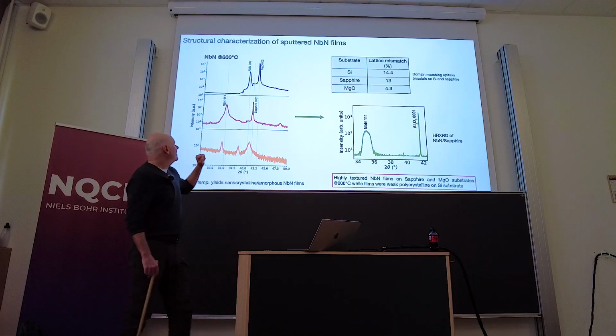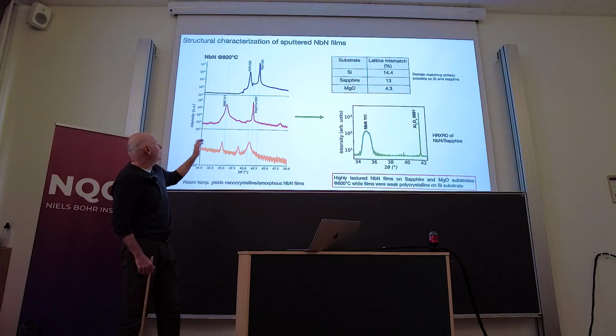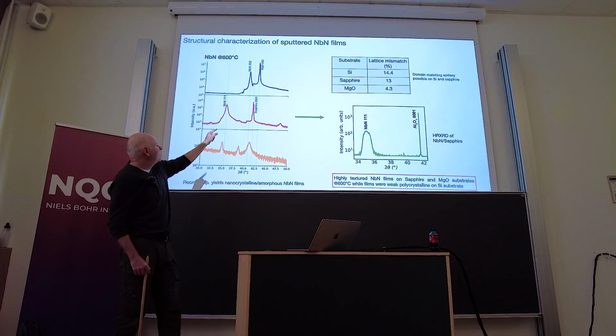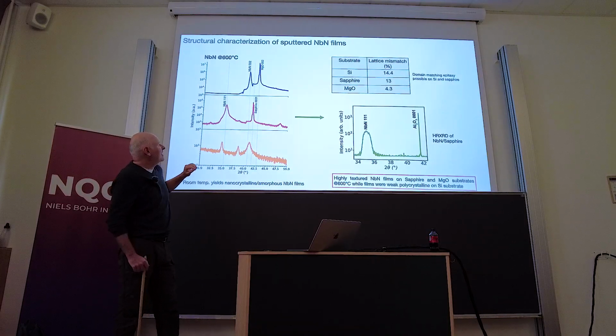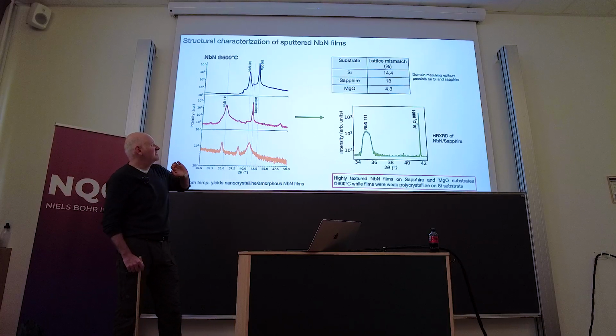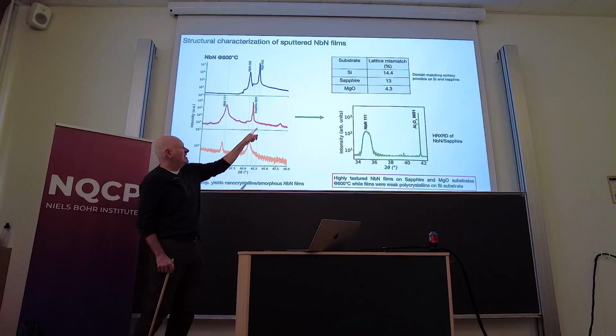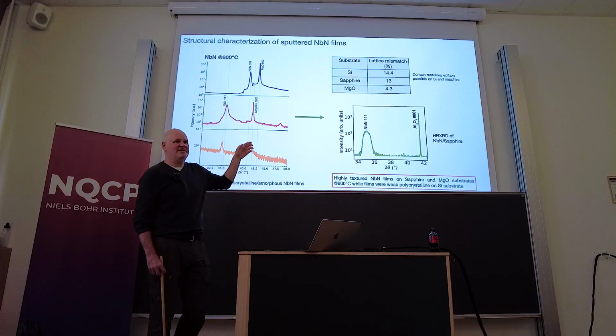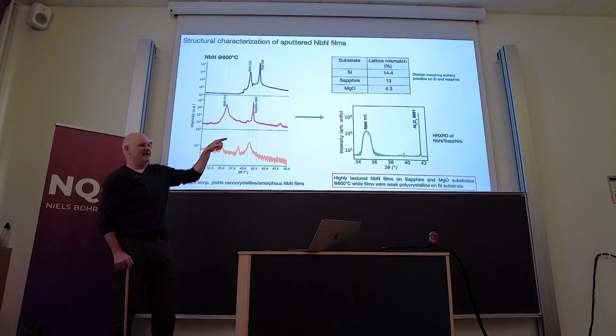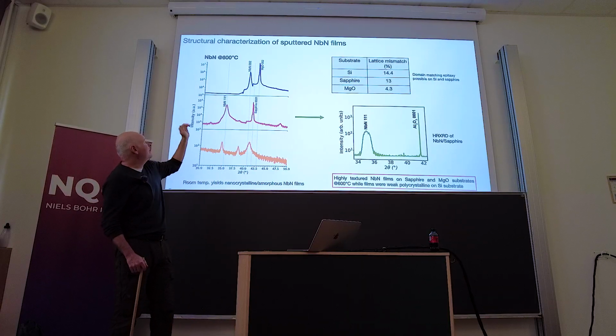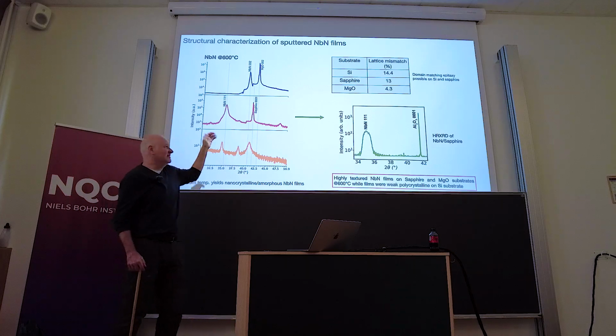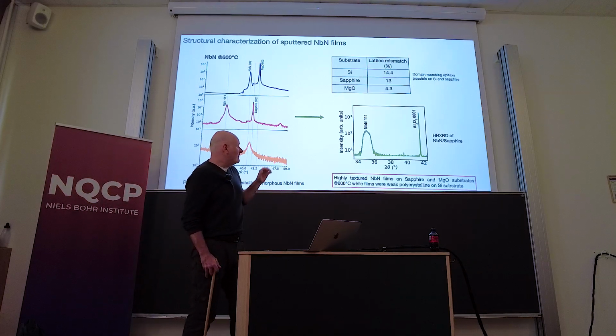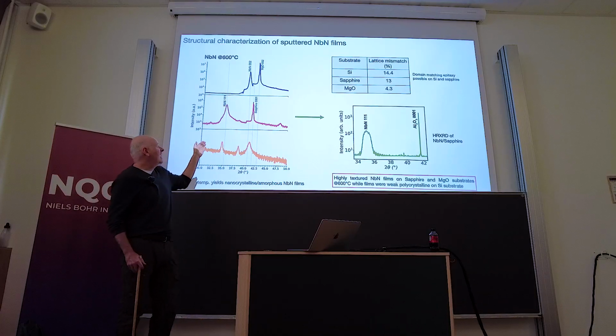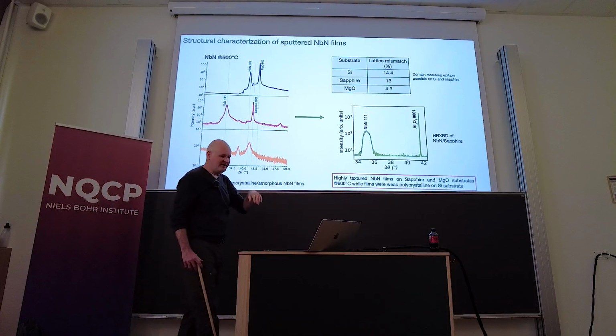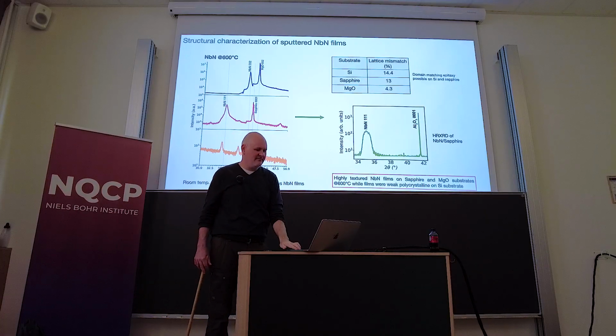So here are X-ray diffraction spectra of niobium nitride on 3 different substrates: magnesium oxide at the top, sapphire in the middle, and silicon at the bottom. And the main takeaway of this is that what you expect to happen does happen, which is silicon has the largest lattice mismatch. So the lattice of the silicon is most different from the niobium nitride. Magnesium oxide is the closest. And as you go from silicon to magnesium oxide, it becomes more and more crystalline. However, on sapphire, even though the mismatch is quite high, you get much better quality materials than you do on silicon. Better quality being more epitaxial and more single crystal.